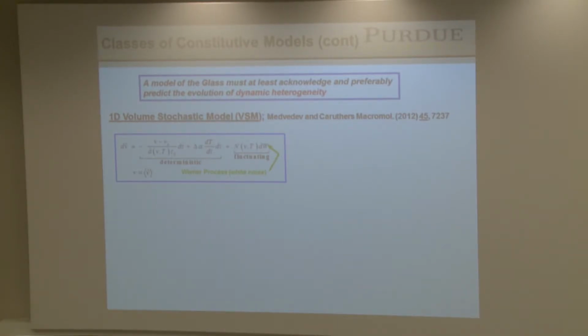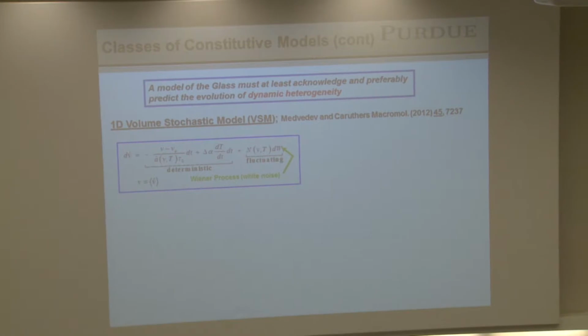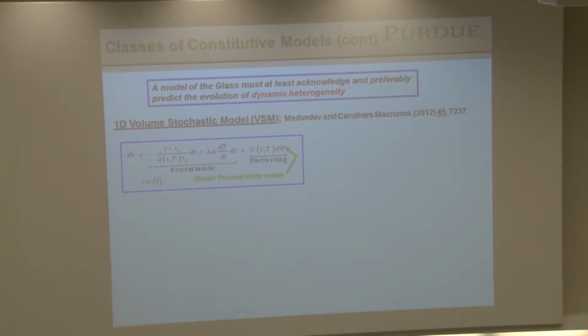And what we said was, maybe what we ought to do, because we have these nanoscale fluctuations going on, is add noise. So all we did was we took the simplest one relaxation process and we added noise to it. And that's a Wiener process. Sorry, Ramke isn't here. He would have liked to have seen his Wiener processes actually used in a chemistry lecture. And we have a coefficient out in front, which is the magnitude of that. But it turns out when you apply fluctuation dissipation, a standard thing in stat mech, it puts a constraint on n, and once you know A, you get n with one parameter, the domain size. And so that's the key model. We just put white noise into a normal relaxation equation.